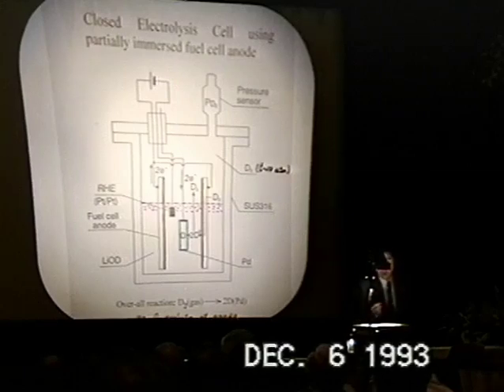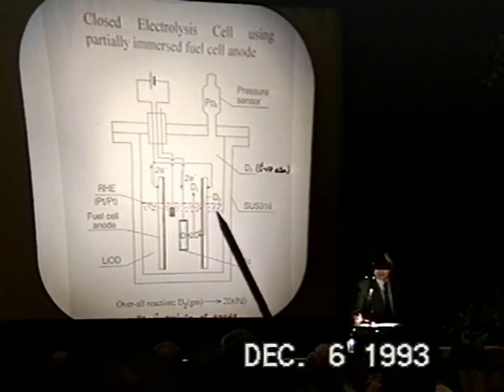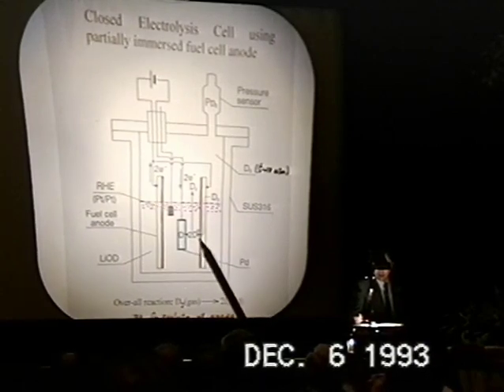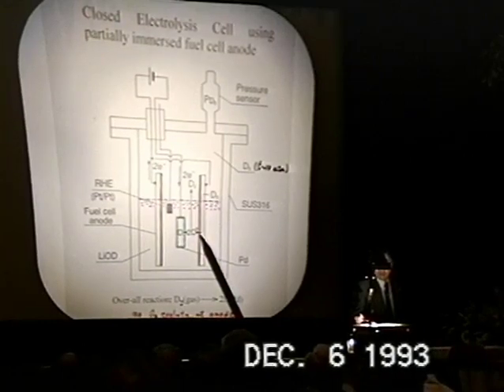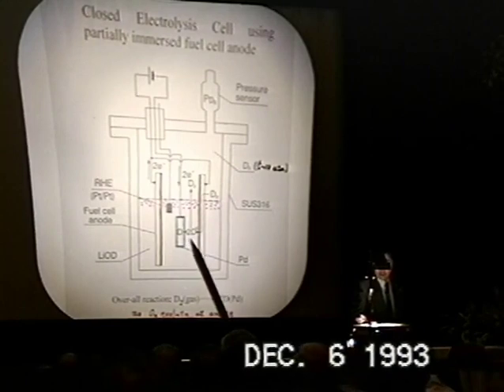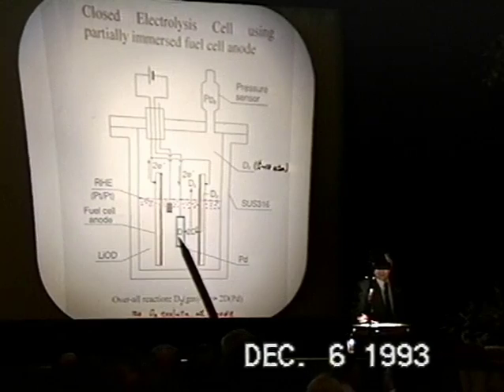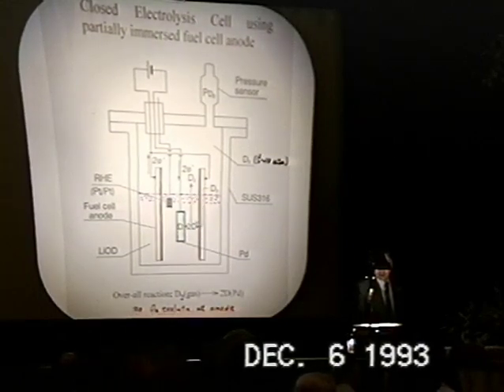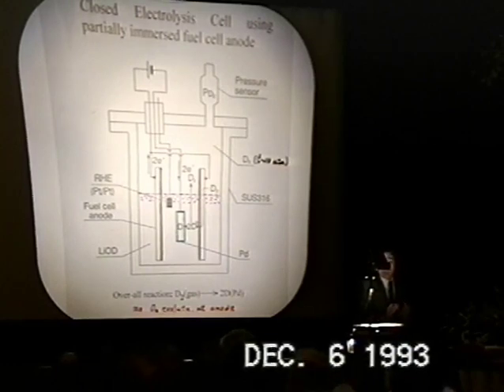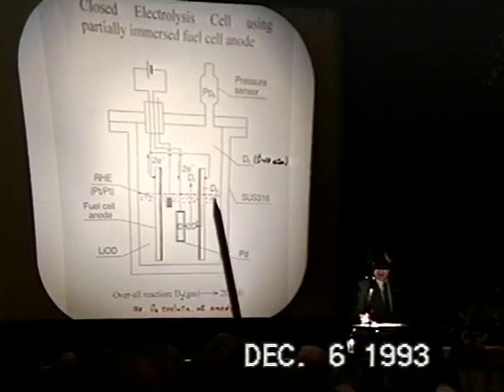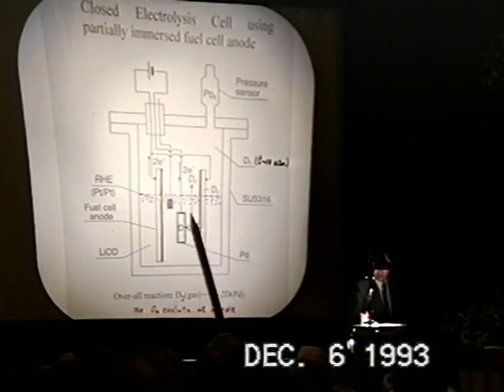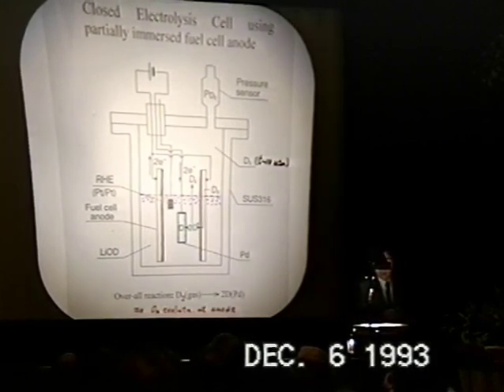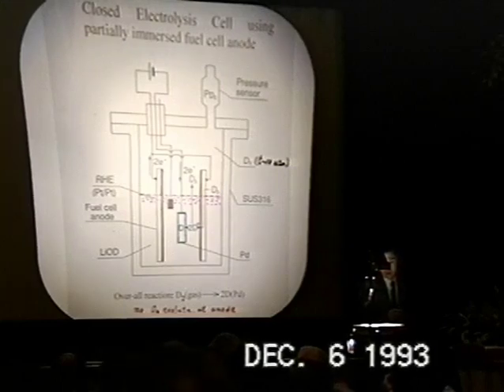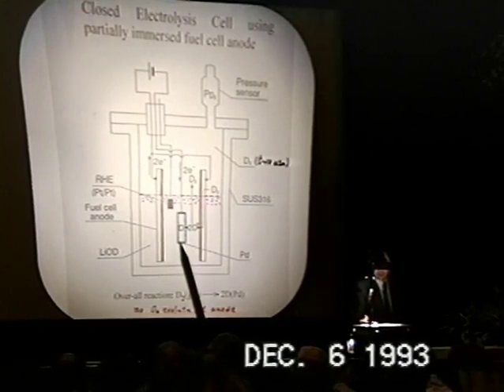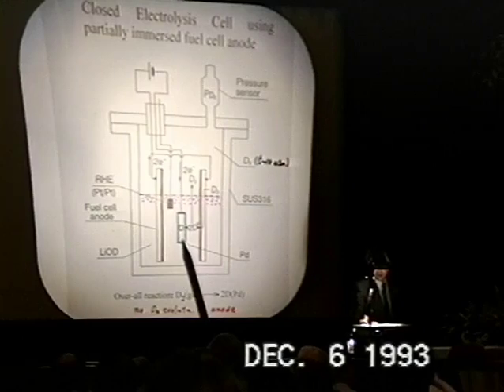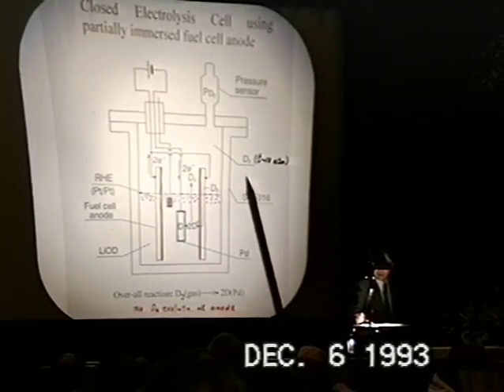If we electrolyze under this configuration, we have the oxidation of deuterium gas molecules to deuterons by the action of the fuel cell anode. And then these two deuterons combine with two electrons from the palladium cathode to give rise to D2 molecules. So if the cathode does not absorb hydrogen at all, then we have just a circulation of heavy D2 molecules. In that case, there should be no pressure change when we switch on the electrolysis current. But because palladium absorbs a lot of deuterium into itself, eventually the pressure of the deuterium gas decreases.